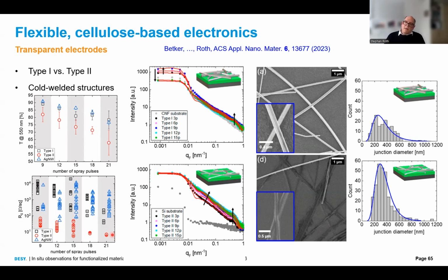And actually you have a combined effect of the solvent evaporation and of the hygroscopic properties of cellulose. They attract the water, and by this they cold weld the silver nanowires. And if you cold weld silver nanowires, they become more conductive. If you just spray silver nanowires on top of CNF, the water is driven away by the CNF layer, and the silver nanowires just lay on top. This is what we see also in the GISAXS. There's not much changing, just we see more material, while we see a nanostructure formation when we spray the mixture. And this nanostructure formation are these junctions, these points here, which we see as nanostructures in our GISAXS signal.